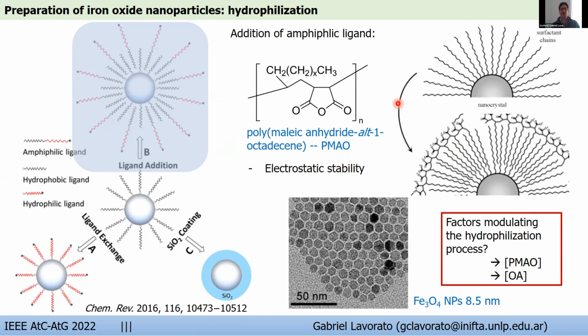So we were particularly interested in the role of the concentration of the polymer and in the role of the concentration of the oleate capping during the process. So we explored the hydrophilization of 8 nanometer magnetite nanoparticles under these conditions. We chose this size to begin this study because this guarantees a zero magnetic remanence at room temperature, and therefore in this way we minimize the effects of magnetic interactions during the process.